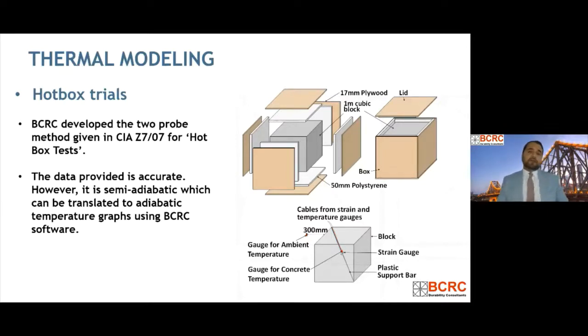So it's a two-probe method. This is how the geometry of a hot box looks like. It's a 1 cubic meter concrete block that you need to pour. And the data that we get from this hot box test is very accurate. However, it is a semi-adiabatic test, right? You have to keep that in mind.